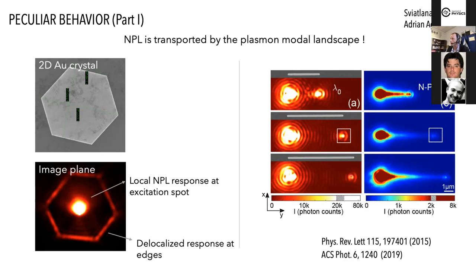Okay, now if you spectrally integrate the anti-Stokes part of the signal, so you're just collecting the NPL, getting rid of the pump, you also have this delocalized NPL signal coming from all over the nanowire. So basically the whole structure is glowing itself. Okay, and you can nicely appreciate how far this NPL extends all the way to the very end. And our understanding of this is that this surface plasmon is carrying the energy of the pump, right? And during propagation, locally brings the electron gas to elevated temperature and then re-emits as NPL signal as it propagates.